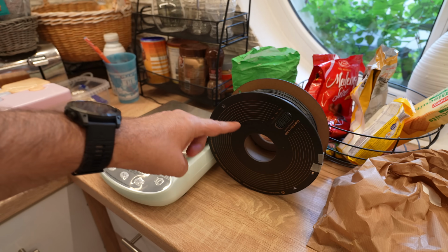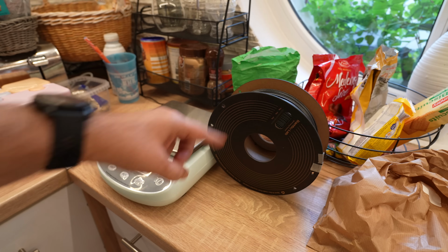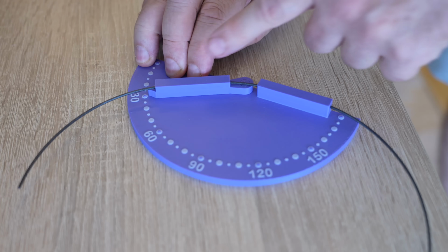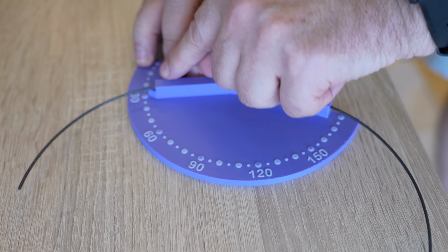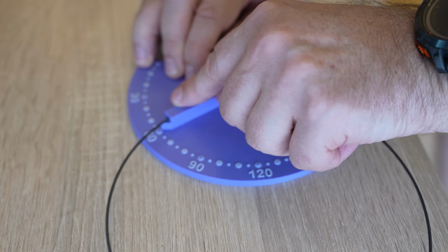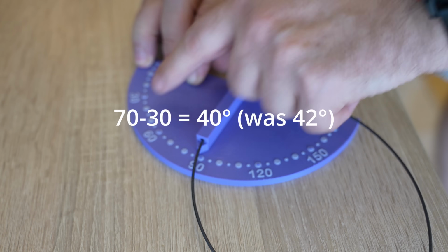I can measure changes in both filaments, but definitely more in the PPA, which is nylon, even if it is stored in the vacuum. Depends on the targeted moisture, but PPS was ready for the printing even after 2 hours of drying. PPA was still not. Quickly to check how brittle is the filament after the drying. Start angle 30 degrees. Very similar.